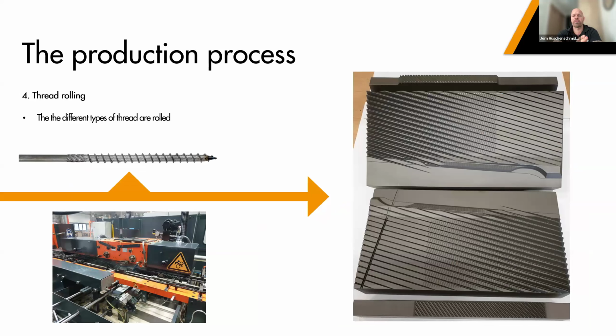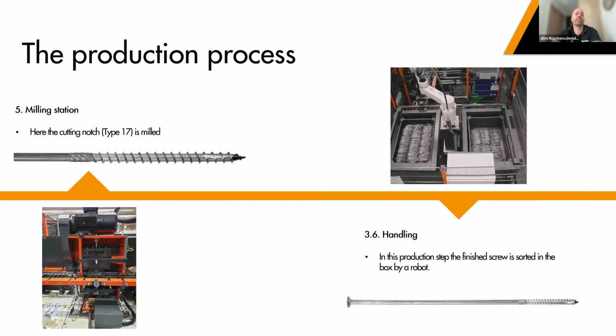So all fully threaded screws mostly start as partially threaded screws. That means by rolling the thread, we stretch the screw, and you see the tip even gets black. So we never actually induce any heat in the process. The heat created is just due to the material moving. So it's always cold forging and cold rolling. Any heat occurring in the process is just due to the material getting hot by dissipating the energy of the forging process. The next step then is maybe a milling station.